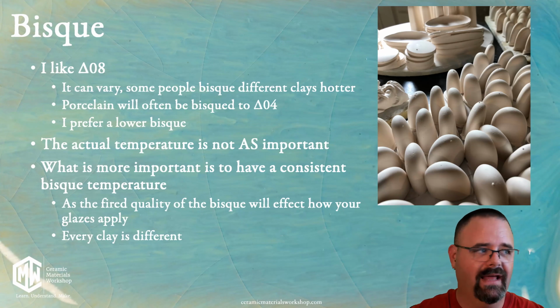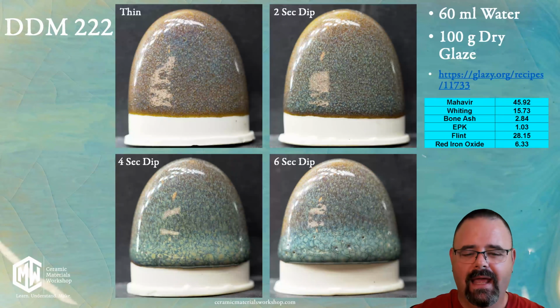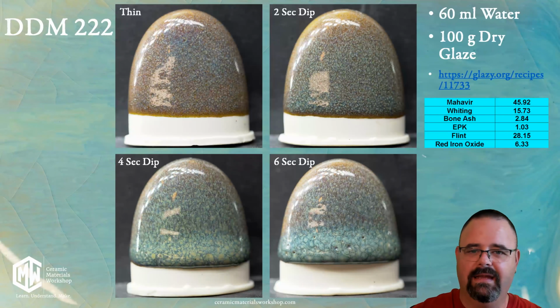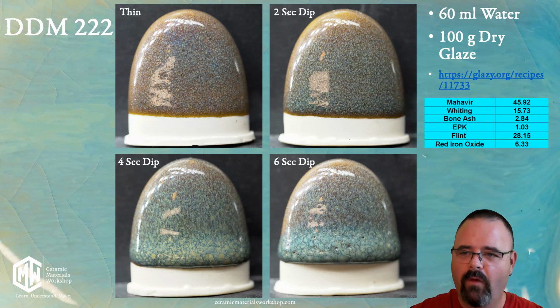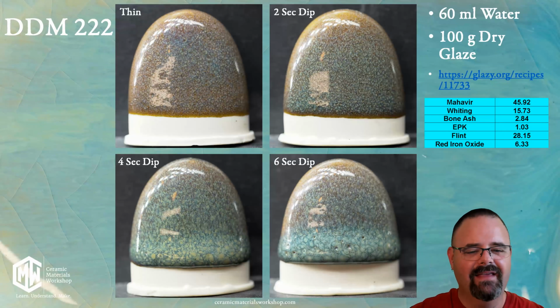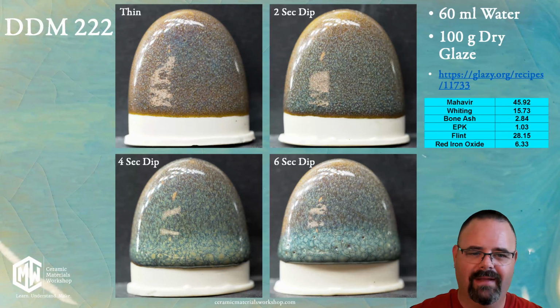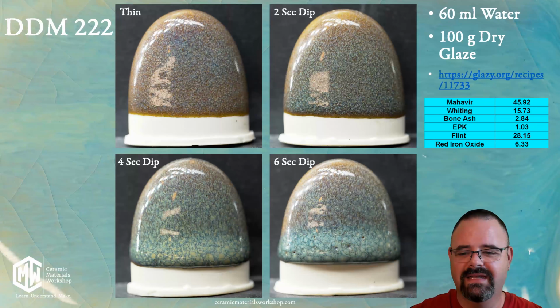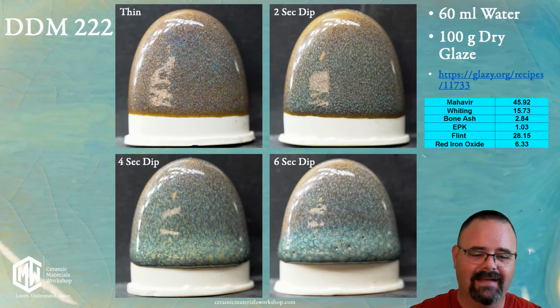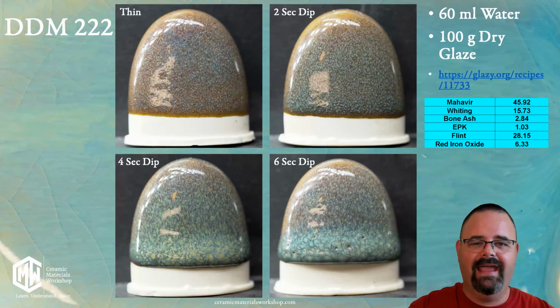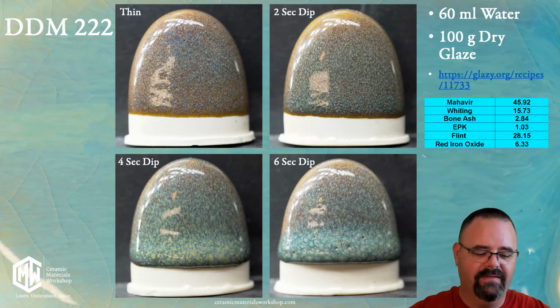And what do I mean by that? Well, let's look at a glaze. Here is a glaze called DDM222, and you can find it on Glazy. Its formula is right here. But what we have on the screen is 4 different test tiles. And the thing is, these 4 test tiles are exactly the same glaze in exactly the same firing. The only difference is how long I applied the glaze onto the tile. This was all done with dip, but we've got in the upper left-hand corner a very quick dip, then a 2-second dip, a 4-second dip, and a 6-second dip. And you can see the effect of this glaze changes radically as you get a thicker and thicker application.